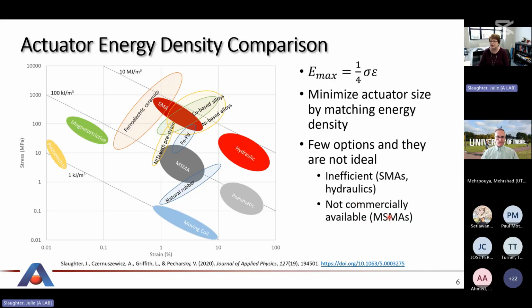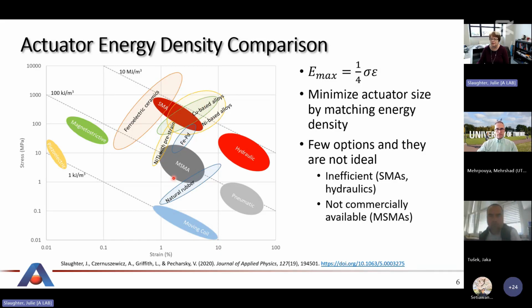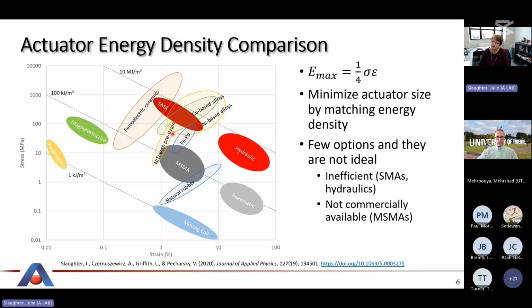So just start and look, a very basic comparison is what is the energy density of the elastocaloric material, what does it require, and then what actuators are available, what do we have available for actuators. So if you look at this, it's a little bit busy, but what we have is stress and strain, and these lines are the constant energy density. So in the transparent ovals, these are different families of elastocaloric materials. And so you can see we have ferroelectrics, we have nickel-based, copper-based, iron, palladium, natural rubber, and then, there's nickel titanium with pre-strain. I've got an example later that will talk about that.